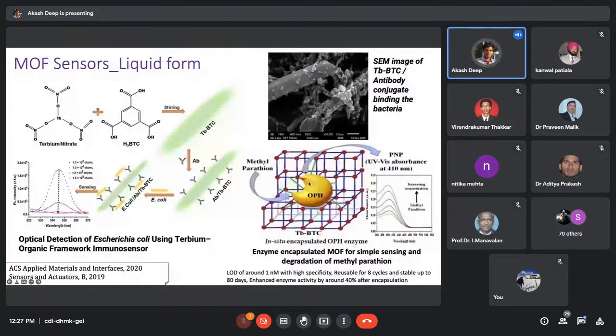So this type of sensor has also been used for the detection of pesticides in water and food samples. This is just to show that these very simple solution based sensors could be very sensitive as well. So the limit of detection of around 1 nanomolar with high specificity has been achieved in this case. And this compound was reusable for 8 cycles. Once it was used, we can centrifuge it, we can recover it, and again reuse. So it was reusable for 8 cycles, and it was stable up to 80 days.